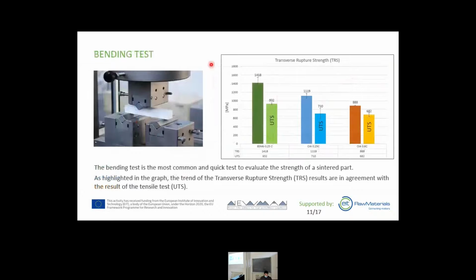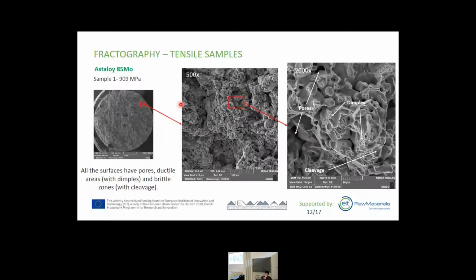production process. We have also carried out the bending test, which is the most common and quick test to evaluate the strength of a sintered part. And also in this case, we see that the trend of the results is the same as the tensile strength. In order to explain the mechanical behavior of the powders and the high deviation of the CRA tensile results, we analyzed the fracture surface of the samples.